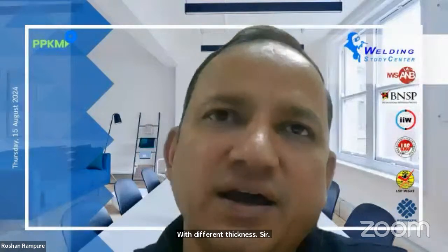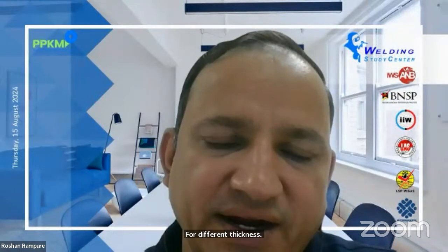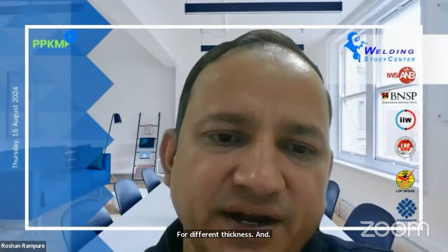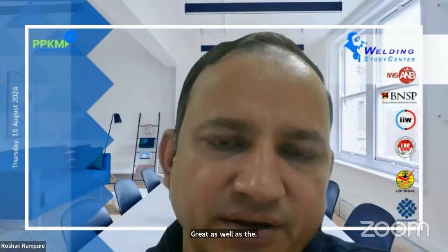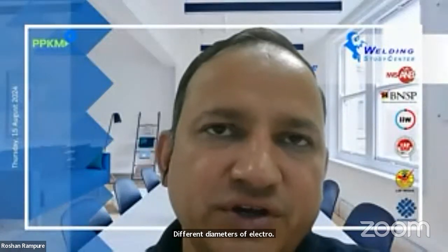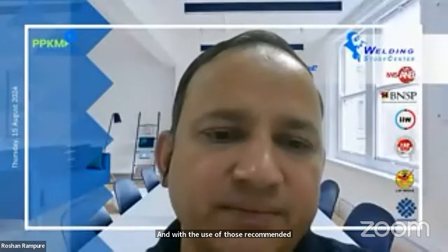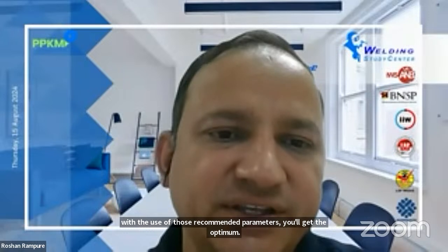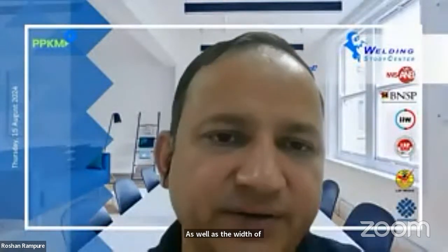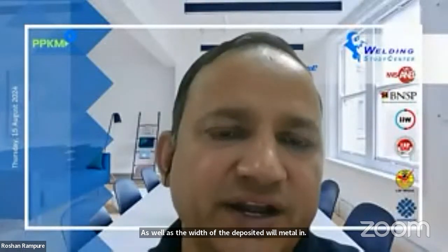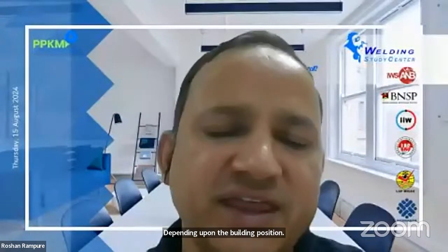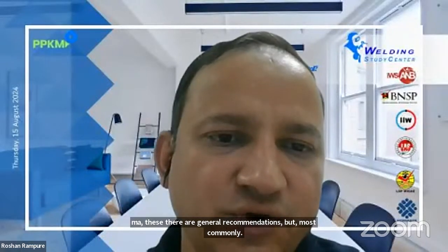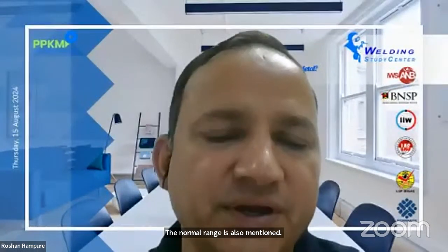There are general recommendations from the welding consumable manufacturer for different thicknesses and different material grades, as well as different electrode diameters. With the use of those recommended parameters, you will get the optimum weld penetration as well as the width of the deposited weld metal in a butt weld, depending upon the welding position. Most commonly, for different grades like stainless steel, carbon steel, and low alloy steel, the normal range is also mentioned on the welding electrode packets.